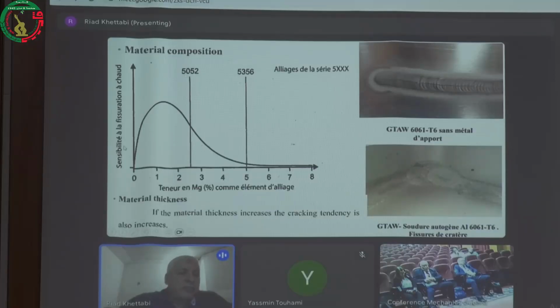Right, and the graphic here shows the sensitivity, or the tendency, of hot cracking versus the percentage of magnesium. So when the ratio of magnesium is very low, in this zone, we can easily have hot cracking, but when the ratio of magnesium with aluminum is very high, we can avoid hot cracking. Also, the material thickness is very important. We can take this into account. If the material thickness increases, the cracking tendency also increases. And this is for hot cracking or cold cracking, the same thing.